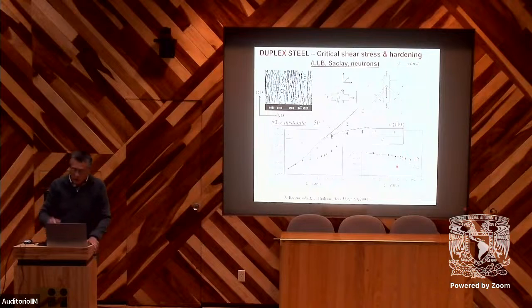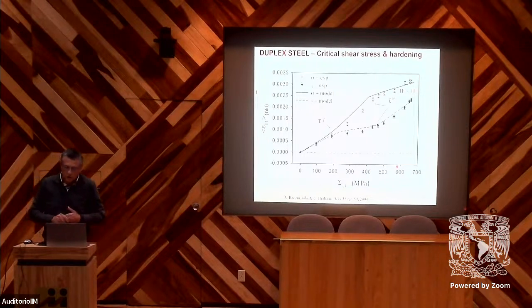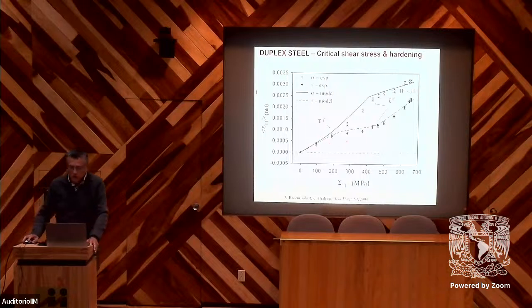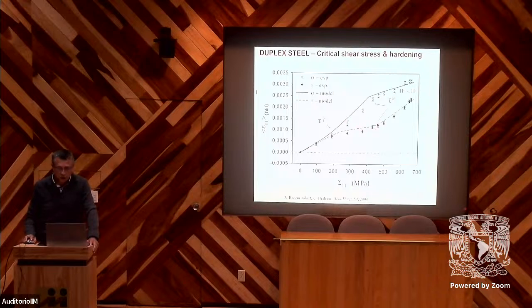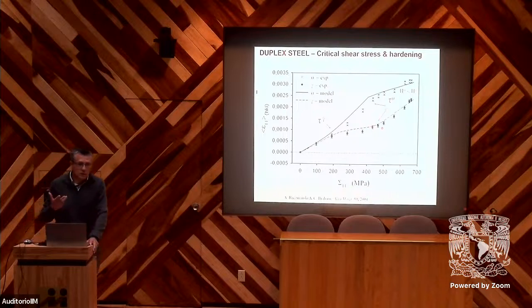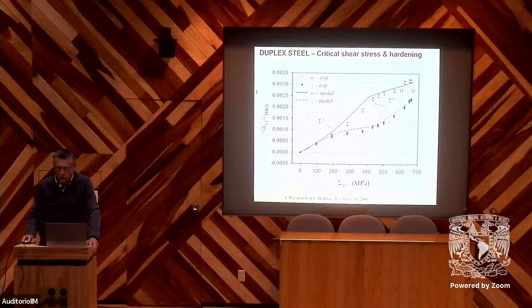If we observe what happens in the direction of the applied stress, at the beginning we have a linear behavior, similar for the two phases. We observe a first critical point corresponding to the beginning of the plastic deformation in the softer phase, here the austenite. Then we have stabilization of the stress in this phase and an increase in the other, the ferrite. When we reach the second critical point, corresponding to the beginning of the plastic deformation in the alpha phase, we again have an increase of the stress in the gamma phase.